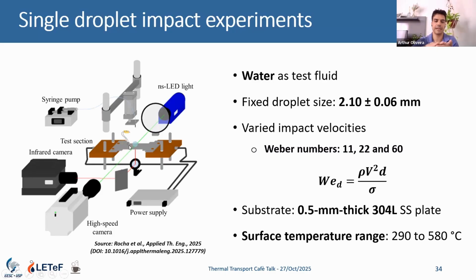It's a very thin plate, so we do a kind of relaxation test. The top temperature and the bottom temperature are virtually the same, so we measure the temperature from the thermocouple and the signal from the camera at the same time, and after we fit Planck's law using the two data. That's mainly possible because we paint the back surface to avoid reflection from the ambient temperature, for example.